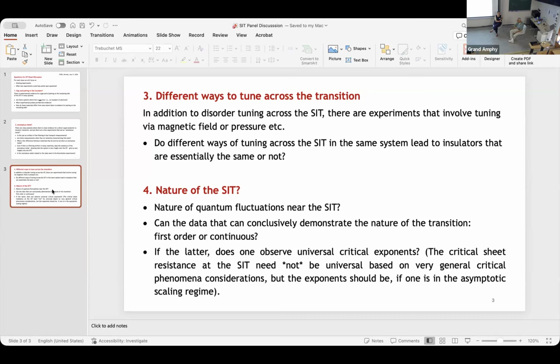I think there's one general problem which seems to permeate that. Matthew Fisher suggested that there might be some self-duality and therefore the critical disorder would be universal, but he would be the first to admit that there's no particular reason why that should be universal. In fact, general critical phenomena arguments suggest that the critical disorder should not. But the exponents, if you can show scaling and show it's a continuous transition, should actually be universal. So I don't know what the experiments have to say about this.